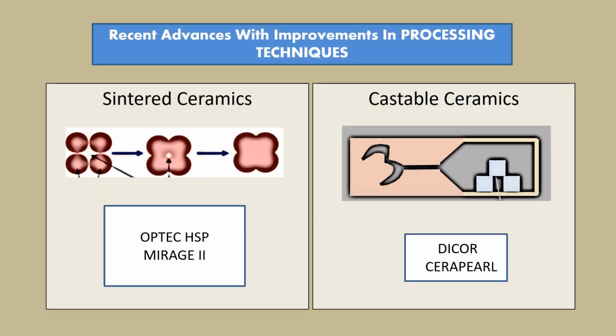Then coming to the recent advances with improvements in the processing techniques, the first is sintered ceramics. In this kind of ceramics, the powder particles are compacted into a solid mass, and this compaction is done by heat or pressure without melting up to the point of liquefaction. That is, we have porcelain powder particles here, and when heat or pressure is applied, the adjacent powder particles fuse with each other at one end, and this serves as a bond between the powder particles, resulting in the formation of a solid mass. The examples are Optec HSP and Mirage 2.